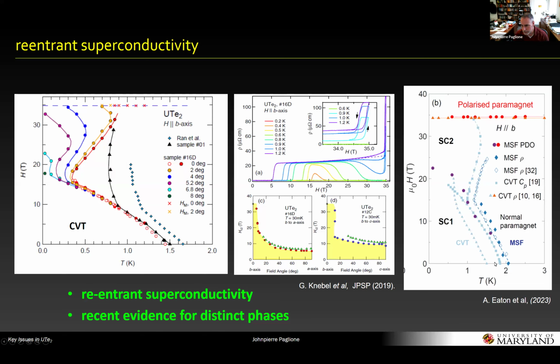And then let's see, so there's more recent data which sort of shows the evolution of this phase diagram for b-axis field with higher TC samples, and you can still see that there's basically the same kind of shape. As you can imagine, the upper critical fields just increase with TC, but there's still this bending back feature that suggests there's a second phase here. And there's also some observation of a subtle feature in heat capacity that suggests there's a transition between these two. But I think that's also an open field, to try to measure the actual transition between these superconducting phases. And of course, do some measurement that would tell you something about the gap structure and symmetry as you go through this putative transition. But that's not done yet.